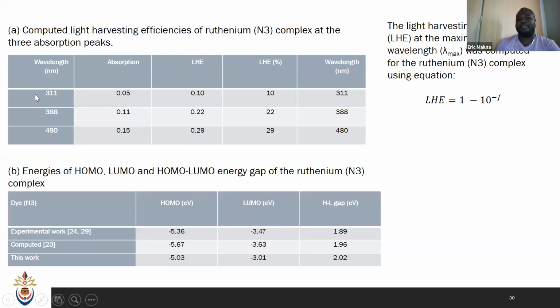And from the different wavelengths, we can see that the light harvesting efficiency of the inorganic dyes is low compared to the other one, which now says that the other one has the advantage. And these are some of the work which has been done compared to what we found here. And we also see that our work is similar to other work which was done experimentally and computationally.